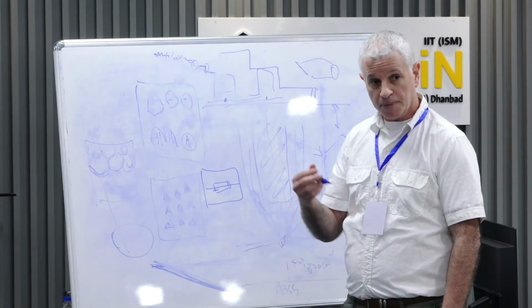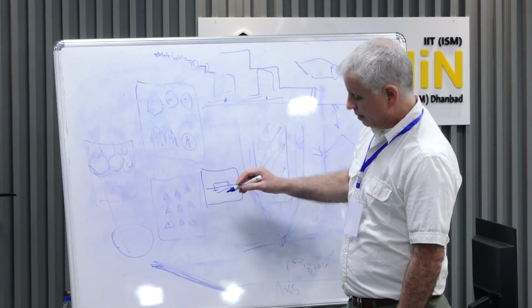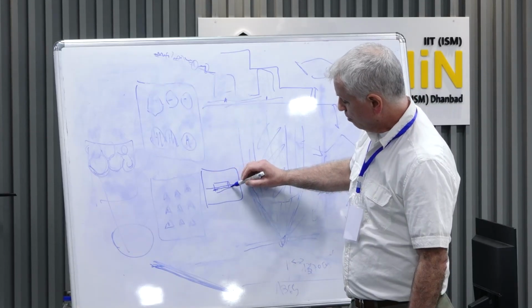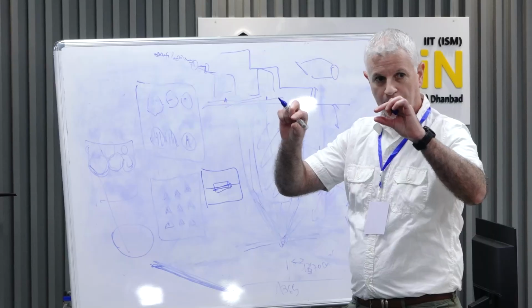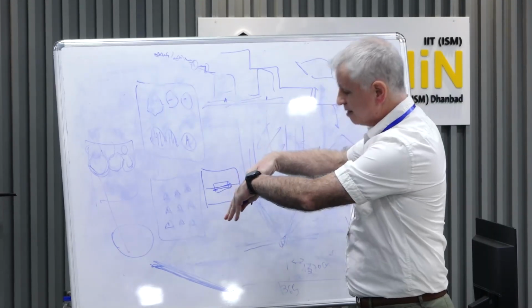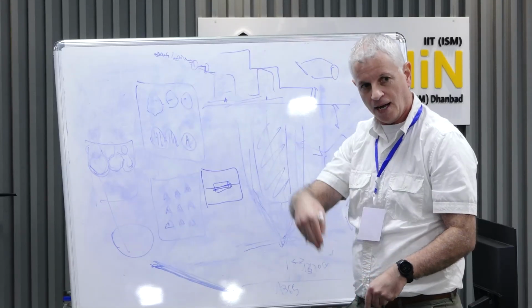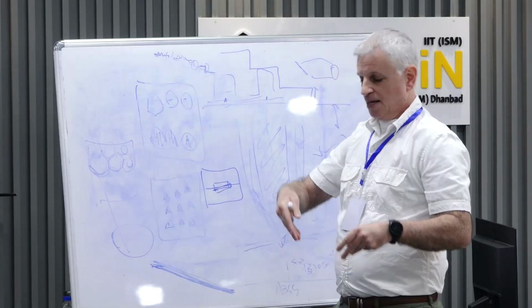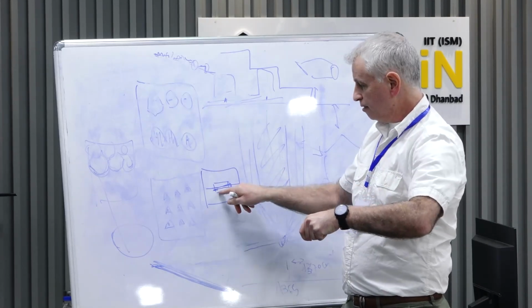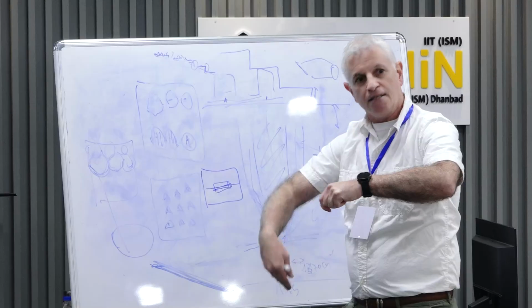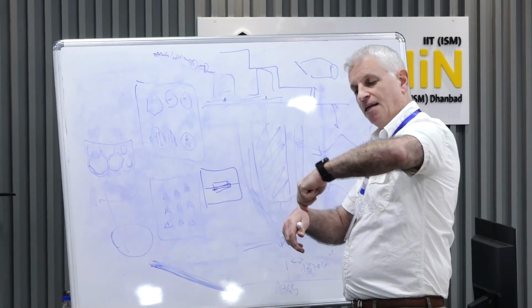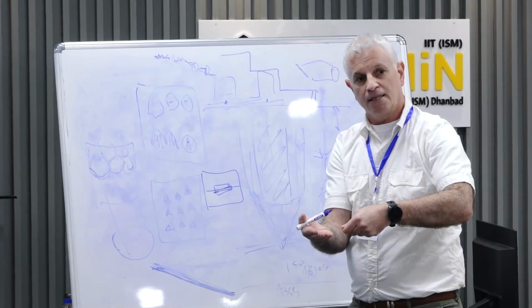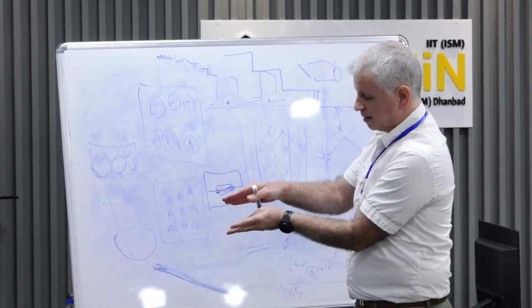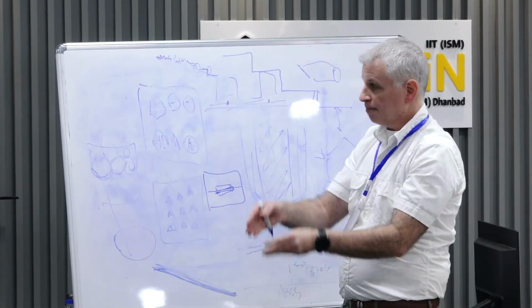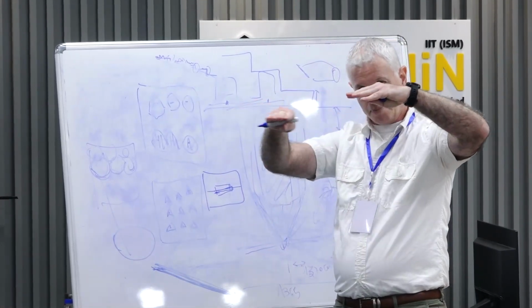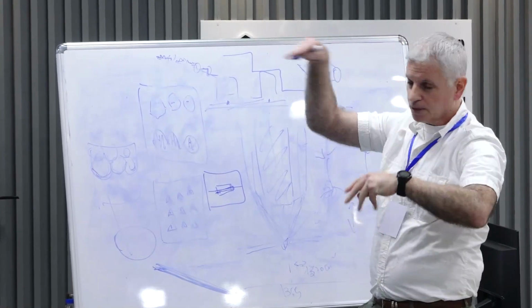It's very energetic, and sometimes it causes a lot of defects. But when you do it right, you prepare a very narrow lamella. Basically you take the sample and you scan with the ion beam, and then rotate it and scan. And then you need something to catch the lamella, and you cut, basically you disconnect the lamella from the substrate, and then with the manipulator you place it on the TEM grid. You basically take it like that, and you rotate it so the cross section is parallel to the plane of the TEM grid. And then you put it in the TEM and you measure.